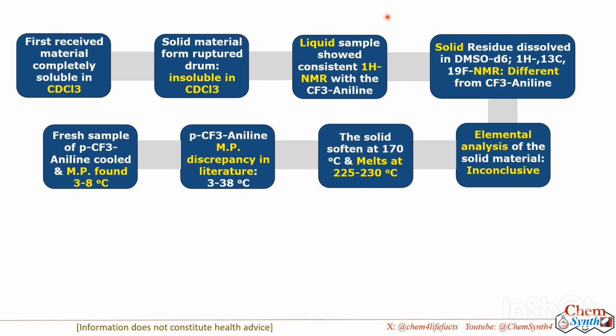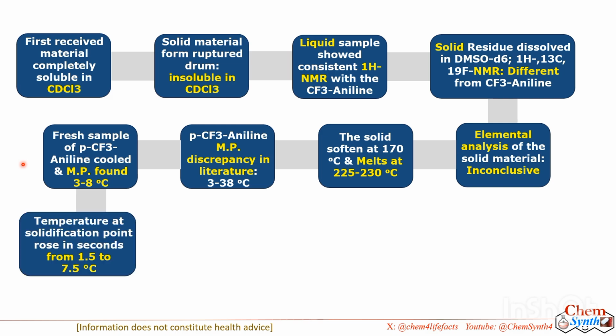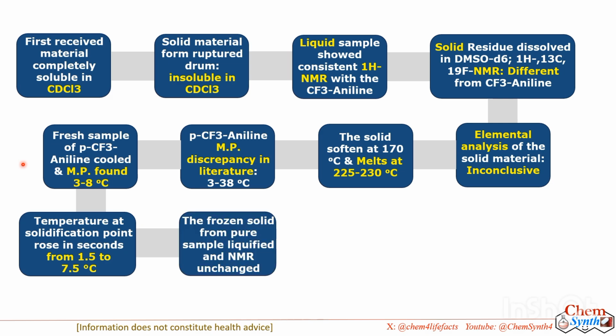So for that reason, they wanted to freeze that liquid sample to get correct information about the melting point. And they observed that the melting point is actually ranging between 3 to 8 degrees Celsius. They also found that it actually solidified at around 1.5 degrees Celsius, and during that solidification process, the temperature immediately shoots up to 7.5 degrees Celsius. For that frozen solid from the liquid sample, they also recorded proton NMR spectra, and it is identical with the original molecule.